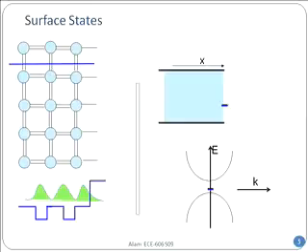After solving the Schrodinger equation, you will have an E-k diagram, and correspondingly in real space close to the surface, the dark blue, do you see it in the middle between conduction and valence band? That's the surface states. These are not foreign atoms. Anytime you cut a bulk material, you are going to introduce one of those states.